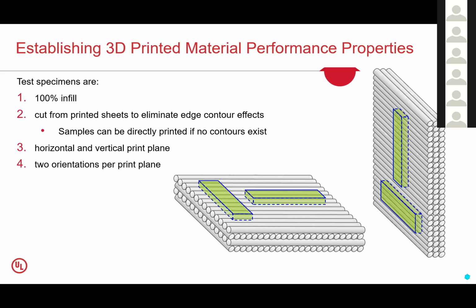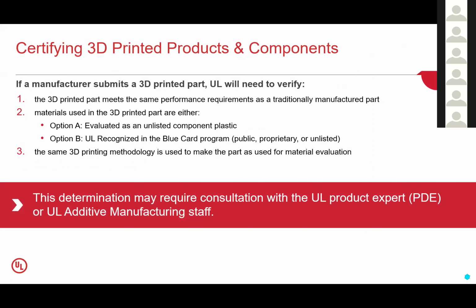So now that we have a nice technique for capturing that information, we can go into looking at how do we certify a 3D printed product or some component. First, we have to acknowledge that ultimately it's the performance of that component that matters. It doesn't matter how we made that component, but whether that component is performing. So the performance requirements are the same, whether it's 3D printed or made through traditional manufacturing. That does not change. If the material has been 3D printed using a blue card recognized material, then we can ascertain whether it was being printed using the same parameters and model printer as what's listed on the blue card, in which case we can expect that performance as what's reported on the blue card, and it can be assessed based on it. If not, we treat it just like any other injection molded part using an unlisted material, where we're going to do the material performance test also.